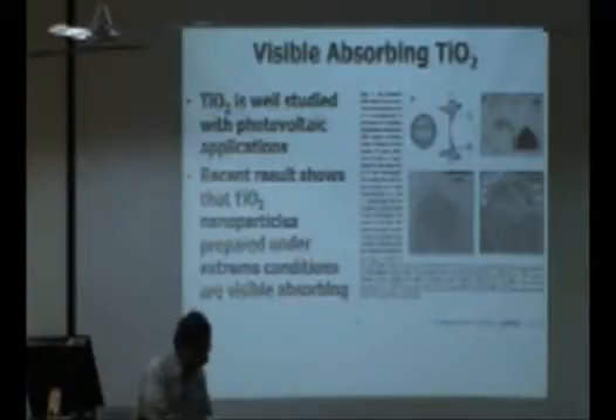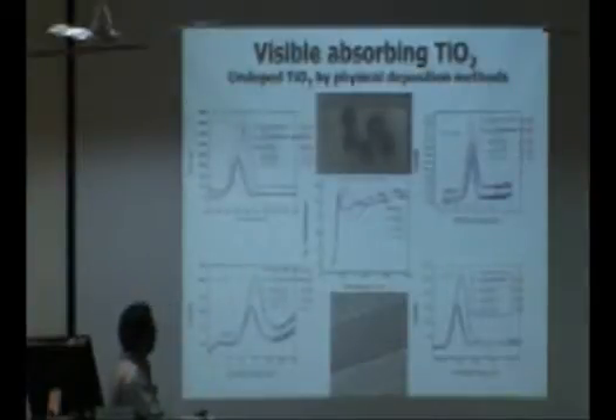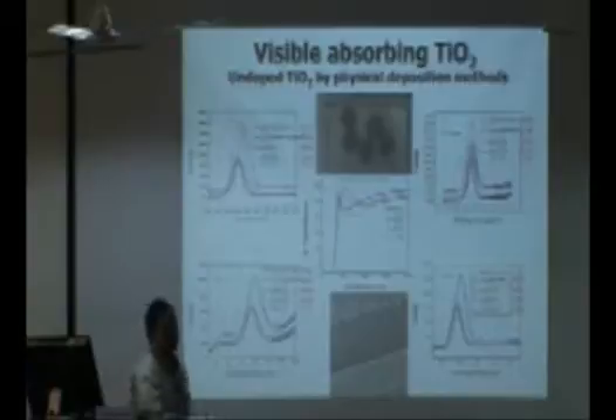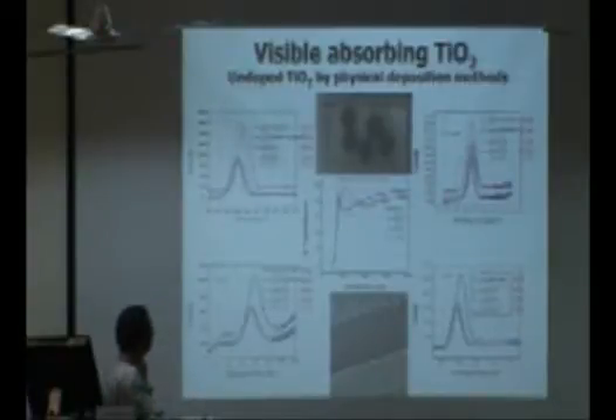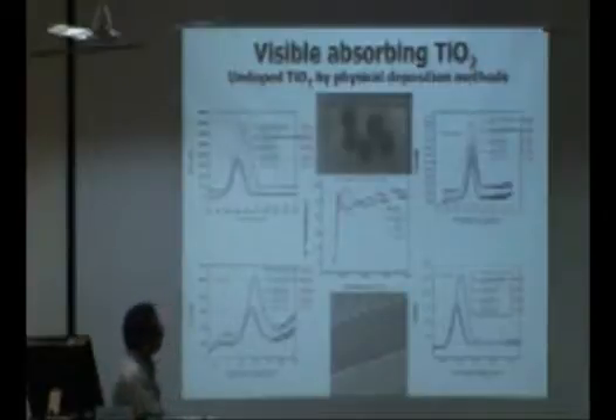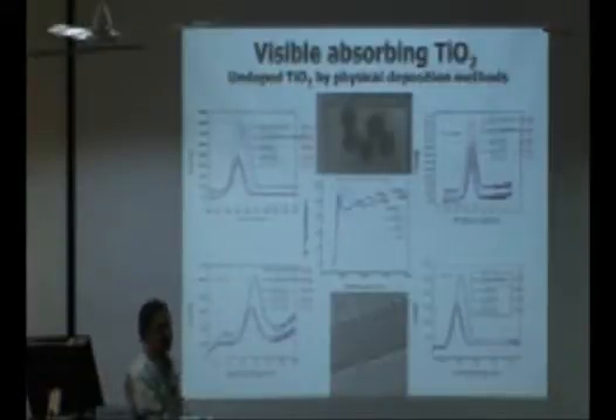What we found is that we can make these dark TiO2 films, or black TiO2 films, which are visible absorbing. As can be seen here, there is almost 40% absorption in the visible range covering 500 to 1000 nanometer, and these are physically deposited using sputtering and atomic layer deposition. We did lots of studies to understand what's happening. Finally the TEM study showed that we have TiO2 nanoparticles here. XPS and other measurements showed that there is a slight shift. XRD shows that these are clean rutile TiO2 particles.